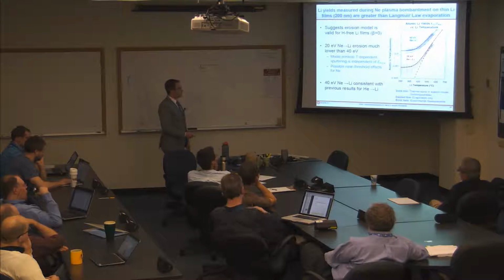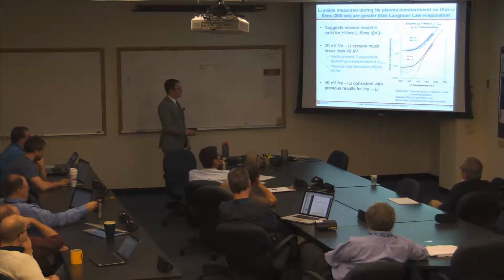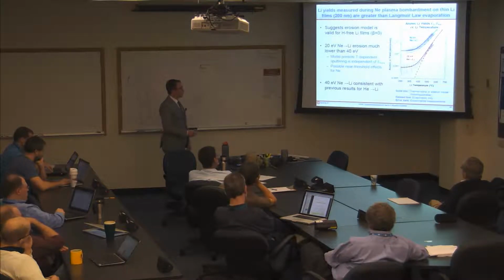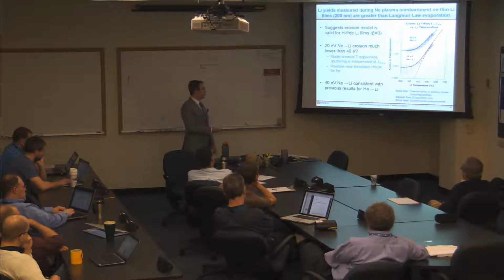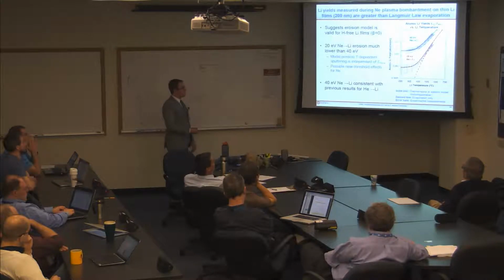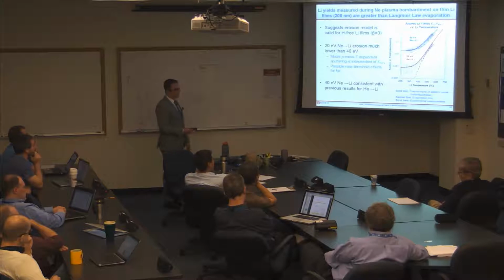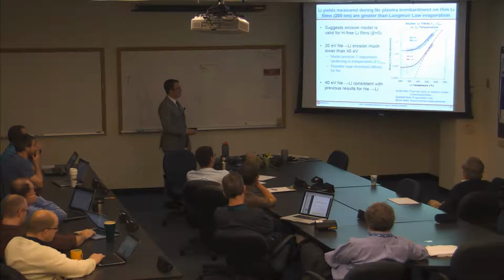So this is the erosion yield as a function of temperature. The amount of erosion you expect just from evaporation is given by this dashed line here. I know these look like amazing fits between predictions and data, but these are just fits I did to the atom evaporation model formula that I showed you earlier. People have never done temperature-dependent erosion rates of neon bombardment of lithium before, so I didn't have any other data to compare it to. But the fact that it is greater or equal to what you expect from Langmuir law evaporation is a nice sanity check that you are getting what you expect. I didn't put it on here, but if you calculate the expected sputtering yield with SDTrimSP, it comes out pretty close, a little lower than the experiment, but within the error bars.